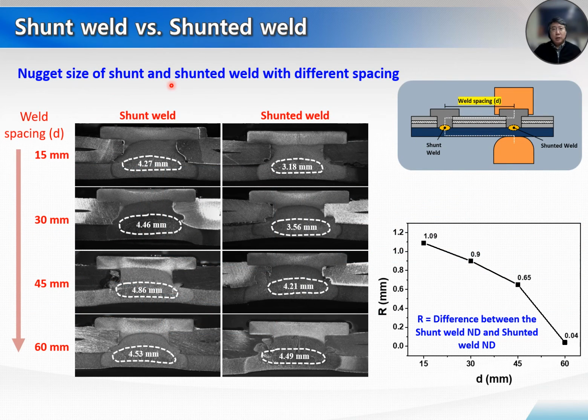In order for a nearby spot weld to play the role of shunt current assisting, it is necessary to derive the minimum weld spacing distance. Additionally, a maximum weld spacing distance that does not require a compensation current value is also required. The difference between the shunt weld nugget diameter and the shunted weld nugget diameter becomes almost zero when weld spacing is above 60 millimeter, which is the minimum distance for no compensation current. However, if the weld spacing is too large, more than 70 millimeter, shunt current assisting is no longer possible for one-step REW, resistance element welding.